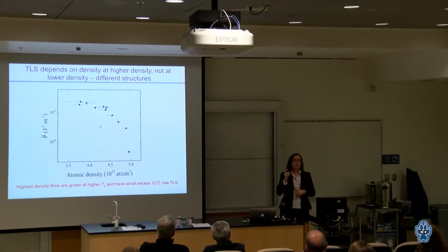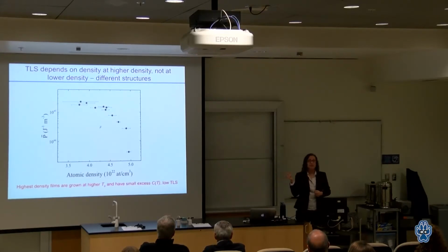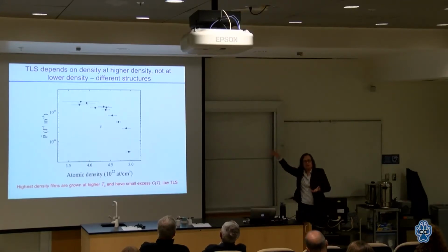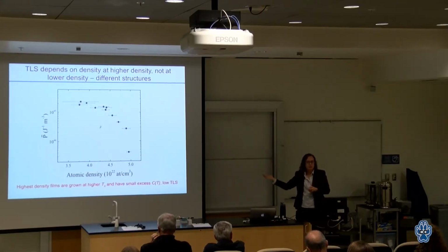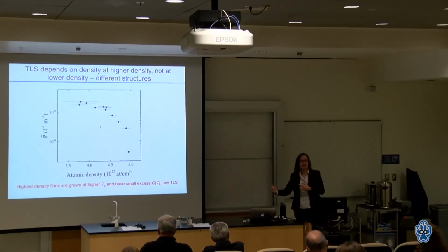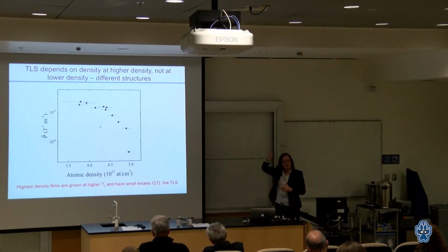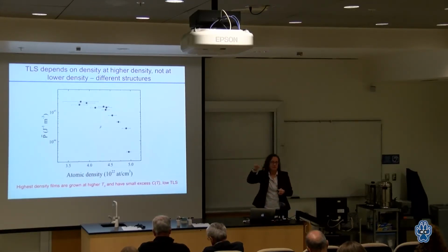Now, what would happen in all cases is if I anneal it, they relax. And as soon as they relax, they lose that structure. You might have even noticed that there's a turnover, like the anisotropy went up and it turned over. That turning over is where the bulk is starting to have mobility. And as soon as the bulk has mobility, it tends to relax. So all of these interesting anisotropic effects happen in the temperature range where I have lots of surface mobility but absolutely no bulk mobility.